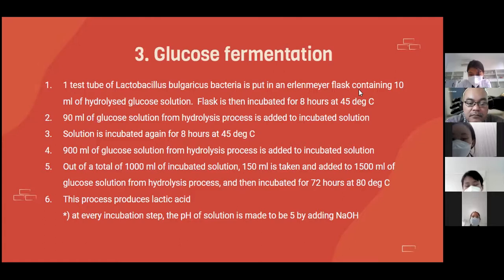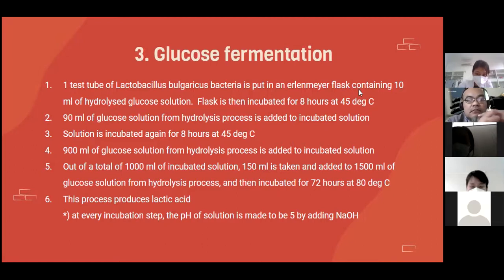And from this incubated solution, 150 milliliters is taken and added to 1500 milliliters of glucose solution from the previous process, and then incubated for about 72 hours at 80 degrees Celsius. And this process is the one that produces the lactic acid. There's also a side note that at every incubation step, the pH of the solution has to be made 5 by adding sodium hydroxide.